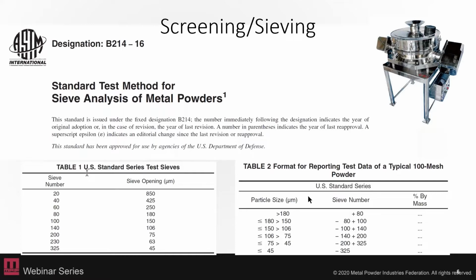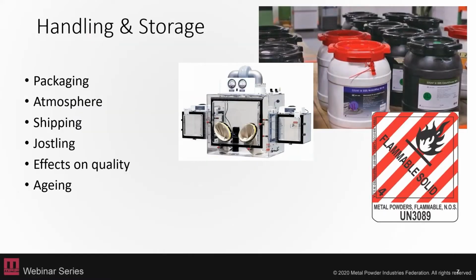For handling and storing these powders, it's very composition dependent on how you need to go about it. With packaging, you need to make sure that your powder is non-reactive with your packaging, obviously. However, there's also other considerations such as electrostatic discharge. So if your material may be more prone to sticking to the side of your container, you may need to change your containers. Nickel powders sometimes have that issue.